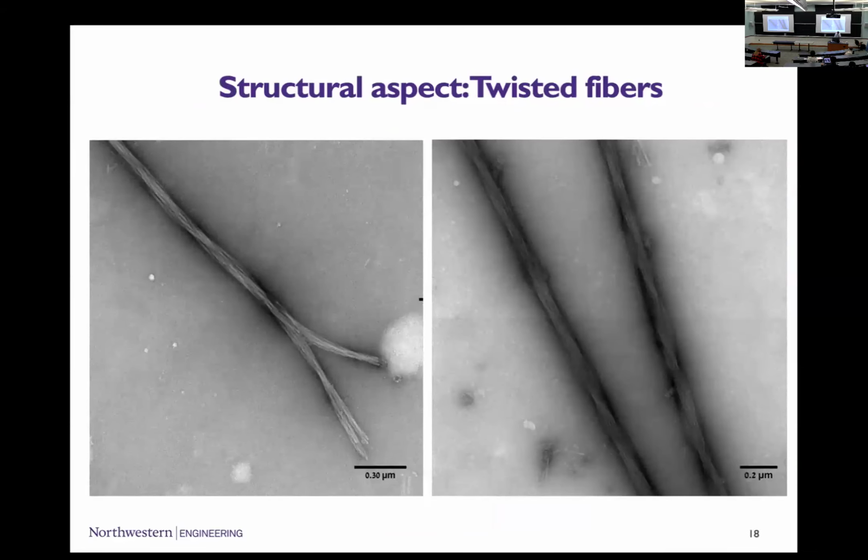So I want to show you one more thing, because it's kind of just cool what a simulation can teach you. If you look up close, you see that these things form almost braided structures, right? Kind of cool. And it's weird, because you can easily calculate there's a torsional energy associated with that. That's not good, right? That is an energy that somehow has to be put into the system. So you think, oh yeah, this is out of equilibrium. Just wait long enough and it will relax. So okay, if this is out of equilibrium, I can accept that, but it also looks strikingly ordered. You can actually look at these bundles and they have a very regular pitch, not what you expect from something out of equilibrium.